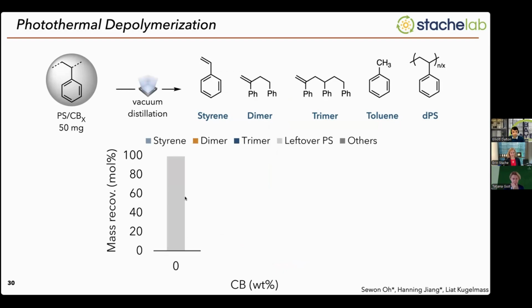And what we found is that without any carbon black, the polymer is completely inert to visible light irradiation. It doesn't do anything, it doesn't degrade, it will absorb the light and just dissipate it as heat, but not enough to actually generate depolymerization.